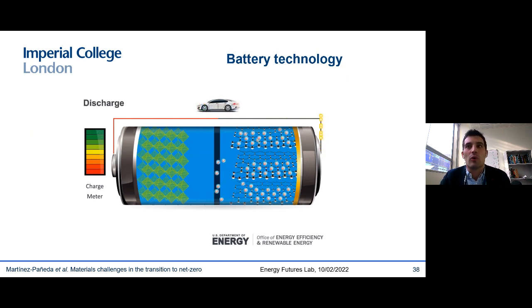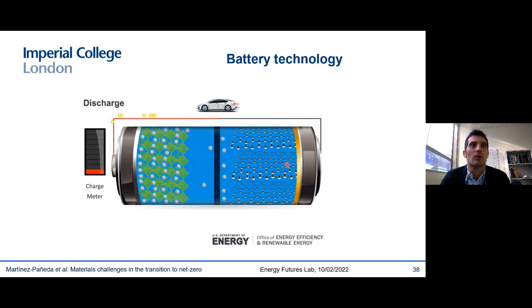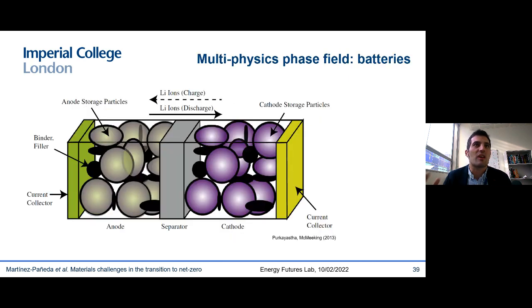And you know how batteries work. During charging, you have lithium ions traveling towards the anode. And when you discharge, the lithium ions go towards the cathode. And material degradation challenges arise as a result of this, and more specifically as a result of lithium intercalation. Because essentially you have lithium being inserted into these storage particles in the anode and the cathode, and this leads to a change in volume and to mechanical strains.